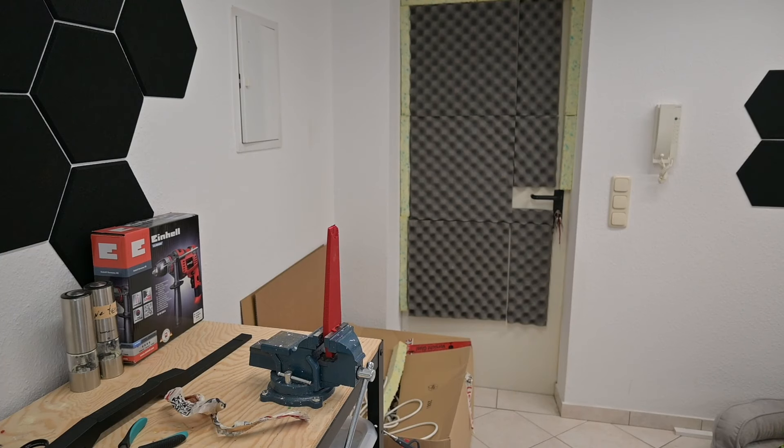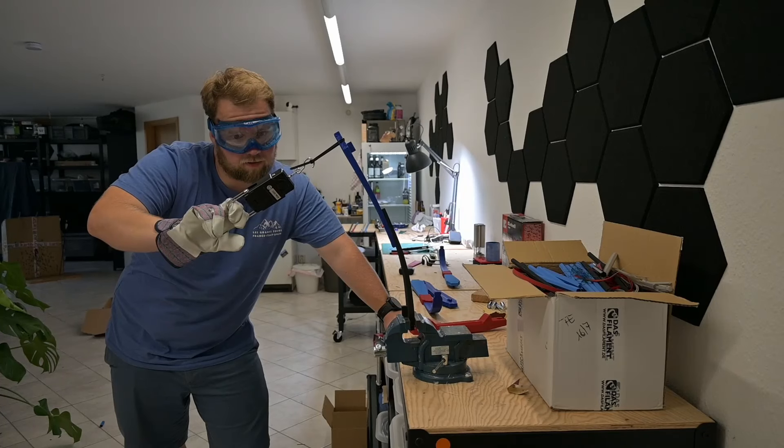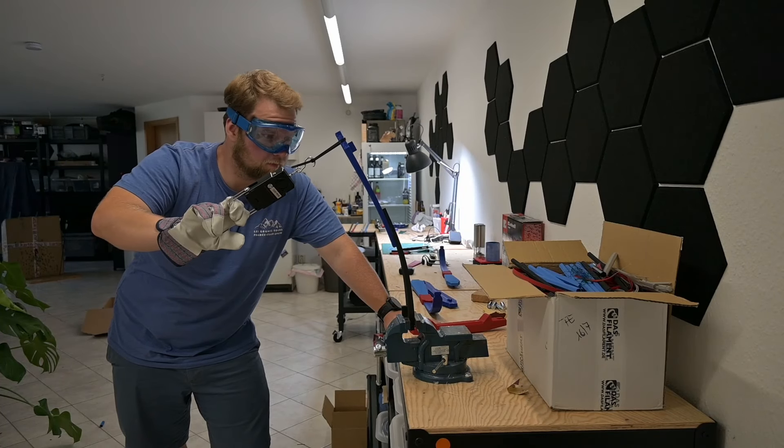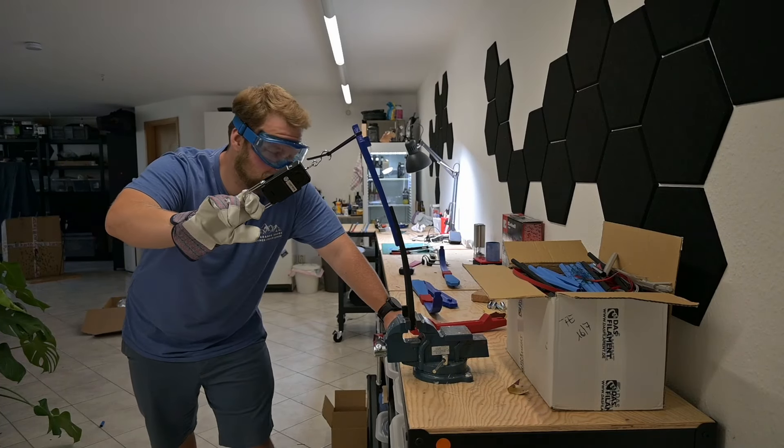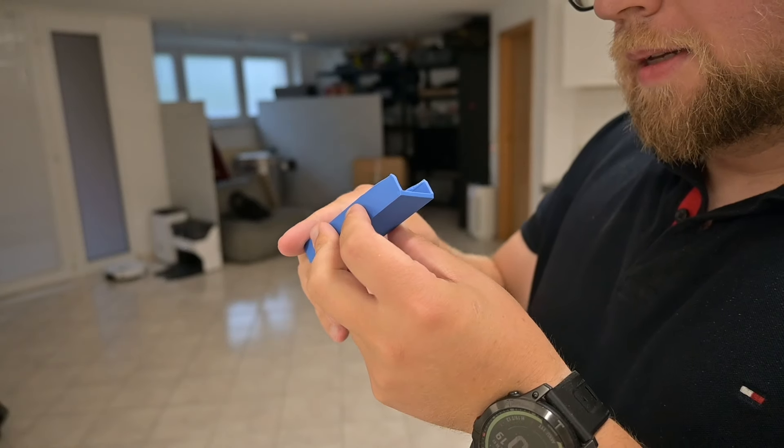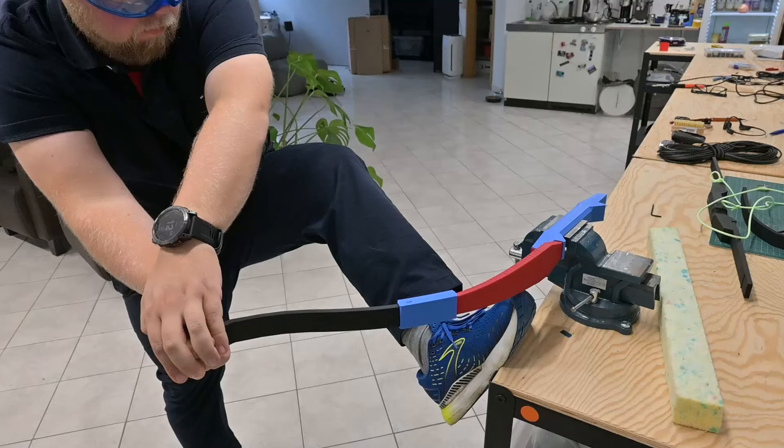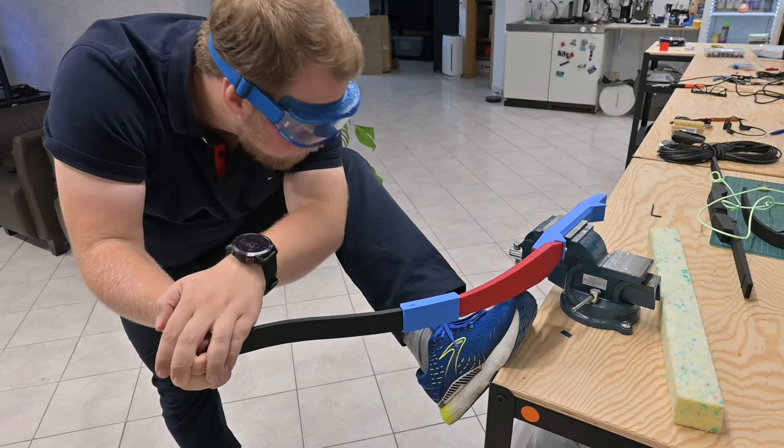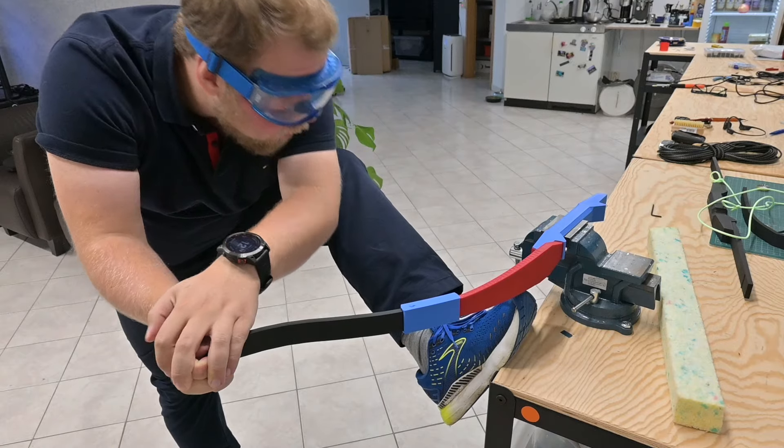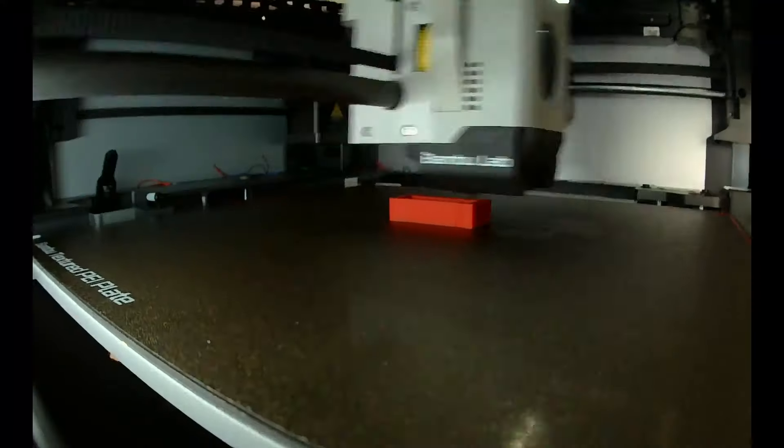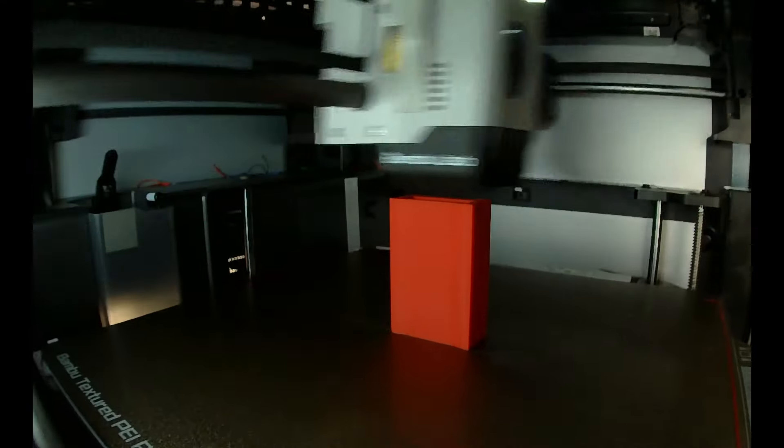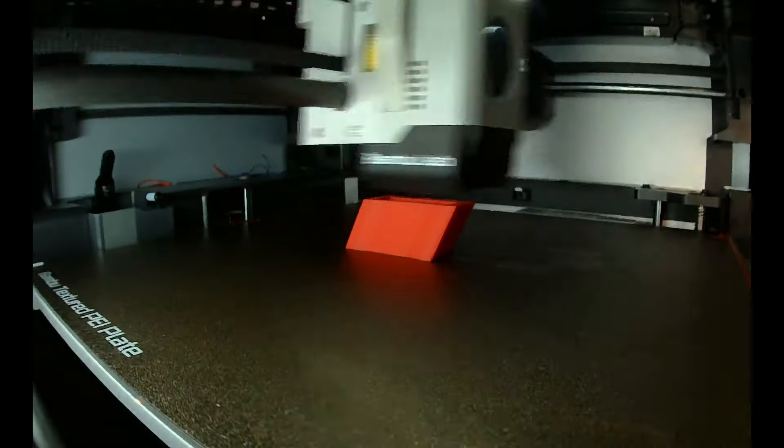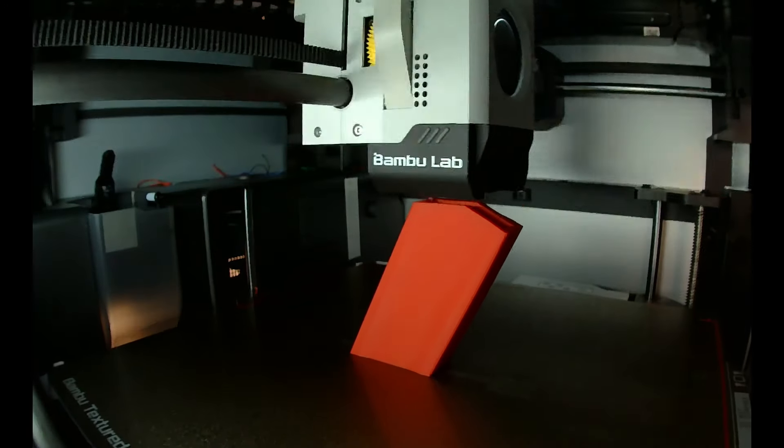So I kept iterating on the initial solution of having a connector, and after some testing I learned I only needed to adjust two things to make this work. Thicken the backside of said connector because, well, it's the part that kept breaking during testing. And also change the printing direction from horizontal layer lines to tilted ones, so the layers create fewer passive breaking points.